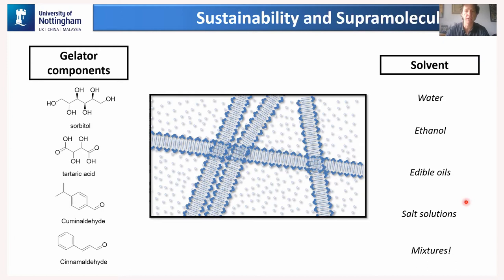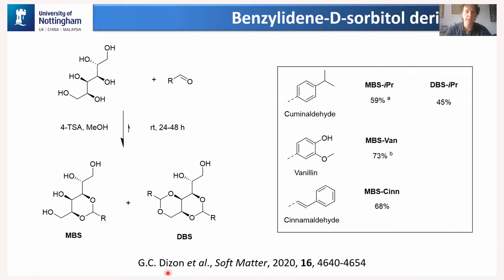So this is work done by Glycine, my group, and it was recently published in Soft Matter. These are dibenzylidene sorbitol derivatives. So here's the sorbitol that I showed you before. And you can take aromatic aldehydes with this sorbitol compound here, and in the presence of acid, that undergoes a reversible reaction where you form a thing called an acetal, which is this thing here. So if you've reacted the aldehyde at this position, that carbon atom is there, and you have the R group hanging off the side here.